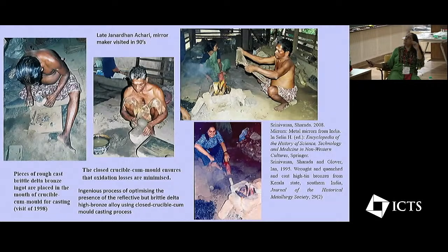Now you also see that this is a slightly different process from what you saw with the casting of the icons, which was an open casting, where you just pour the metal into an open sprue. The reason they made a closed crucible cum mold here is that it helped minimize oxidation of the metal, because when it's open to air, even as you're pouring the metal in, you get oxidation, and that causes a very bad surface, the fire skin which forms and so on. So this was to prevent the oxidation losses, and they were deliberately using a closed crucible cum mold. Here the metal was placed, and then it's all sealed and covered.